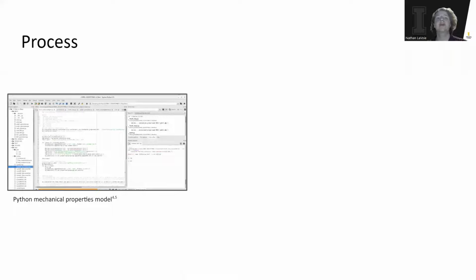Python was used to create a program that took into account Inconel 718's underlying material properties as well as specified microstructures, including grain size, orientation, and arrangement. The program used these values as well as underlying constants and solved millions of calculations based on crystal plasticity, resolved shear stress, self-hardening, and latent hardening models to simulate Inconel 718 under stress. The main algorithm was based around a fast Fourier transformation. Each operation was separated into its own subroutine so that the algorithms could be used and adapted in different combinations.